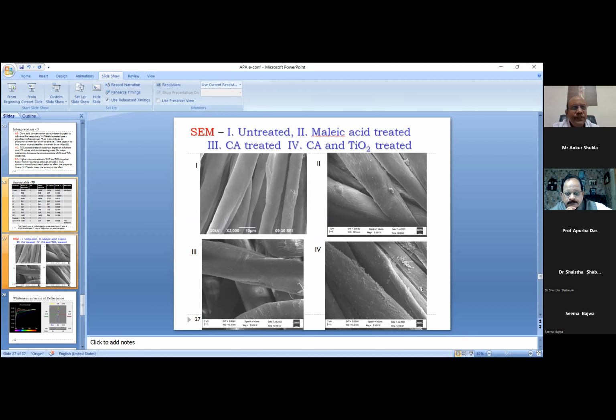And in fact, here we didn't go for a direct pad dry cure method. We first padded and dried without having any TiO2, and then later on it was padded with TiO2. Reason being that in the initial bath when it was taken, the results were not good. And TiO2, as I told you, the dispersion of TiO2 is a little difficult, and we had in fact taken nano TiO2. So the dispersing agent we used in sufficient quantity, and then only the padding was done.